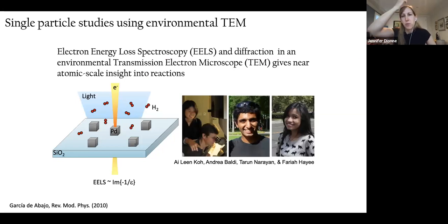We synthesize our nanoparticles using colloidal syntheses, in some cases just conventional syntheses, in other cases new syntheses where we can get almost atomically precise control over the catalyst. And then we're going to use our electron beam and a combination of electron spectroscopy, for example, electron energy loss spectroscopy, to probe the electronic and optical properties of the material. And we also use diffraction to probe the structural properties. And we can do that both with and without illumination.